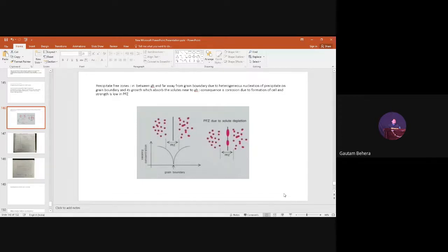Very good. Why are you saying A1 temperature? You can justify it like this: if we have a eutectoid steel, then we have to go above A1, not at A1 or below A1. Basically 30 to 40 degrees above A1, or 50 degrees above A1, if it is a eutectoid steel. But if it is not eutectoid, if it is hypereutectoid, then the condition is different.